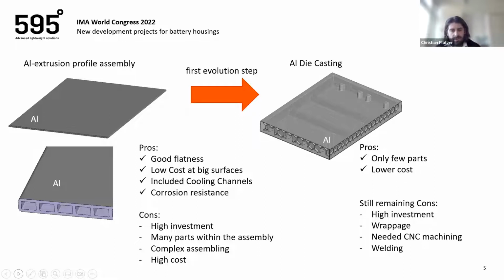As I said, currently mainly aluminum is used to produce battery housings, and they tend to get bigger and bigger. Maybe in future they can get a little bit smaller if the chemistry behind it can be somehow changed or improved. But currently they're getting bigger and bigger. And the first thing that was used to produce those battery housings have been aluminum extrusions or aluminum profiles that got assembled. And the advantages of those aluminum profiles are that they have a very good flatness, which is important because we need to control the temperature of the battery cells in the housing. And this is usually being done by controlling the housing bottom temperature. And the bottom is via heat transmission, influencing the temperature of the battery cells.